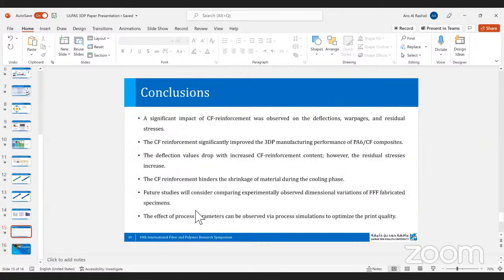So in conclusion, we can say a significant impact of carbon fiber reinforcement was observed on the deflections, warpages, and residual stresses. The carbon fiber reinforcements significantly improved the 3D printing manufacturing performance of these composites. The deflection values drop with increased carbon fiber reinforcement. However, residual stresses increase as we saw. This is due to the reason that the carbon fiber reinforcement hinders the shrinkage of the material during the cooling